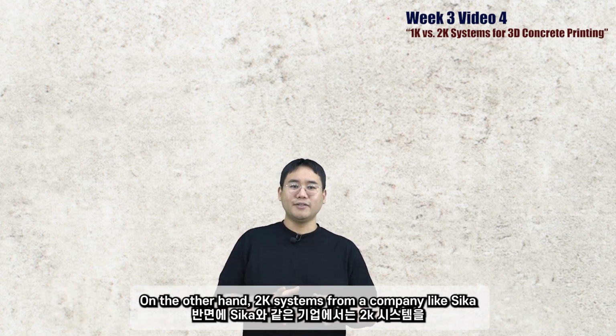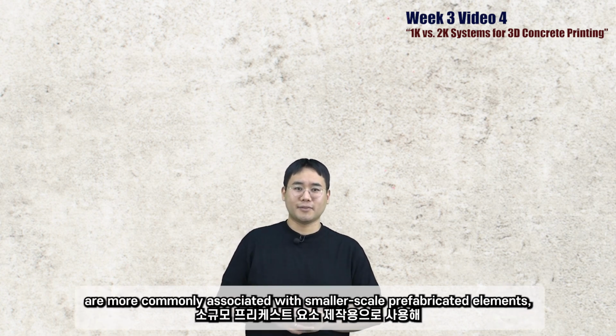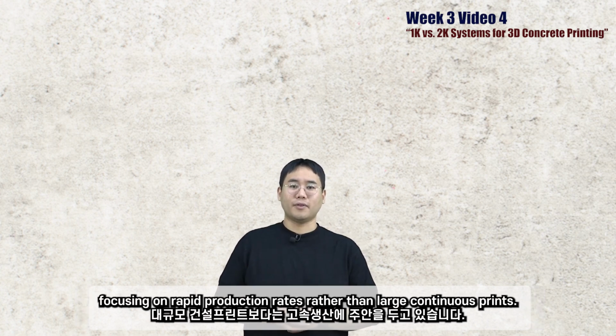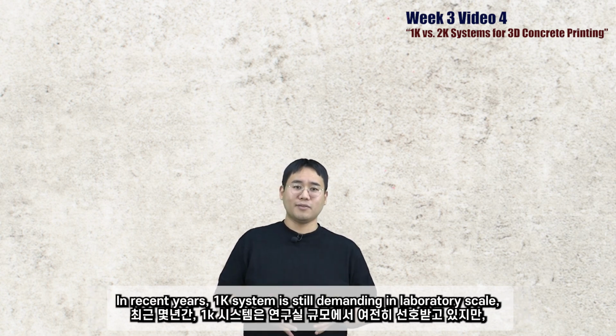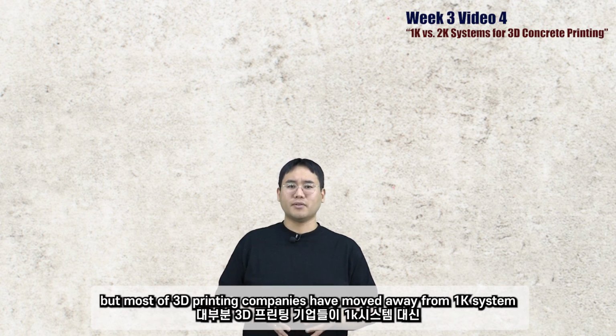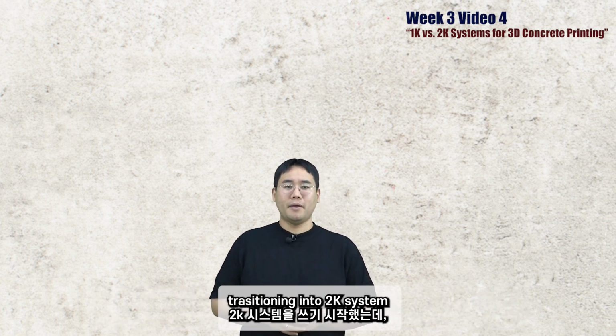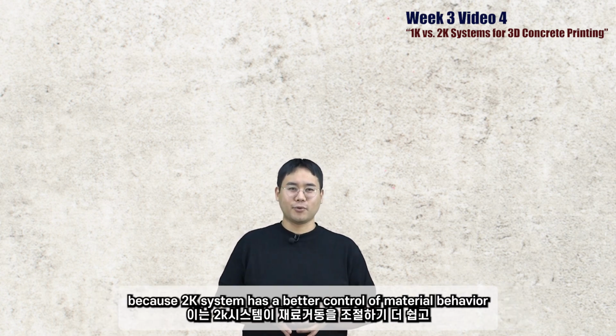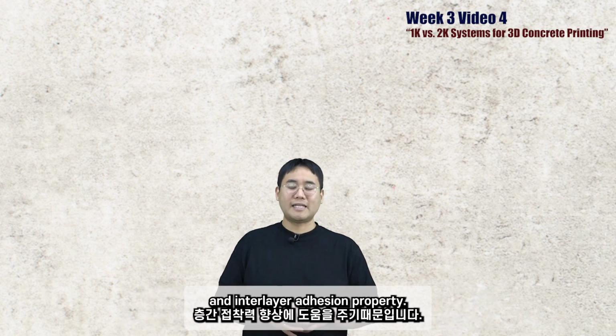On the other hand, 2K systems from a company like Sika are more commonly associated with smaller scale prefabricated elements, focusing on rapid production rates rather than large continuous prints. In recent years, the 1K system is still in demand at laboratory scale, but most 3D printing companies have moved away from 1K systems, transitioning into 2K systems, because 2K systems have better control of material behavior and interlayer adhesion properties.